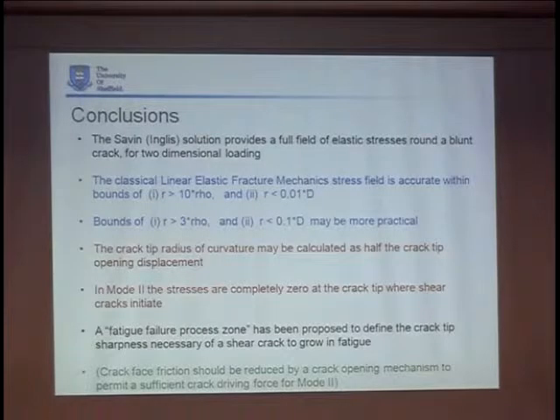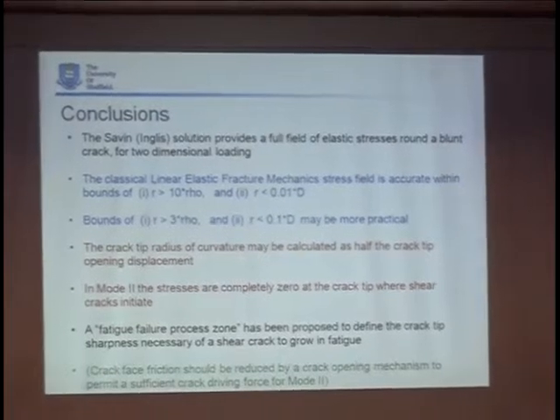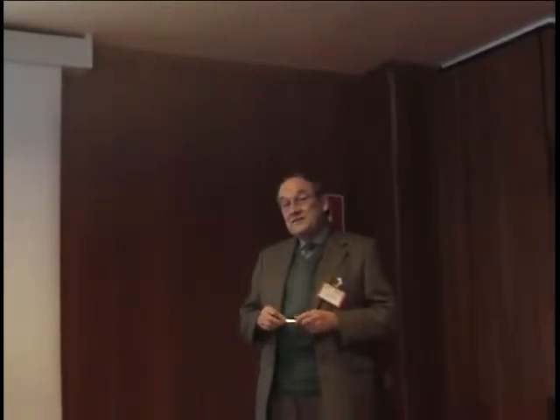Thank you, Mike. So would you have been successful if you had been growing a crack at larger cyclic loads, where your process zone would have been bigger? We took the compressive stress all the way up to yield. But we still didn't manage to, with the cyclic torsion, if you put on bigger delta, it's unlikely we would have got faster mode 1 cracking, really, in that case, because a notch is just a notch, it's too blunt. Yeah, but you would have pushed it out into that region where the stresses are more well behaved. By increasing T, yes, yeah.